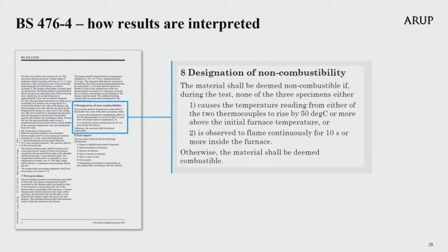Okay. For a tested material to be considered non-combustible by means of this test, none of the three specimens during the test must either cause the temperature reading from either of the two thermocouples to rise by 50 degrees Celsius or more above the initial furnace temperature, or be observed to flame continuously for 10 seconds or more inside the furnace. Otherwise, the material shall be deemed combustible.